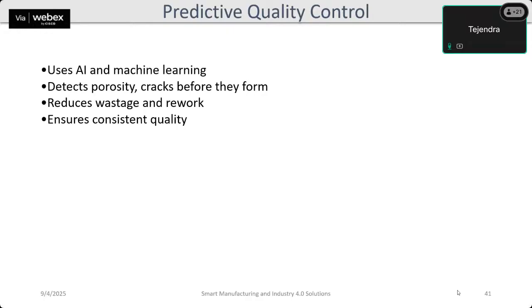The AI algorithm can analyze this data in real time to predict whether a defect is about to occur or not. For example, let us suppose the melt pool temperature starts fluctuating beyond the safe range. The system can predict that porosity or lack of fusion may develop. Similarly, by monitoring the bead geometry, we can warn against layer distortion or poor surface finish.